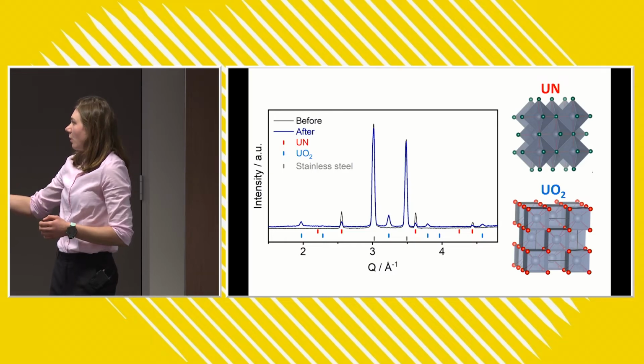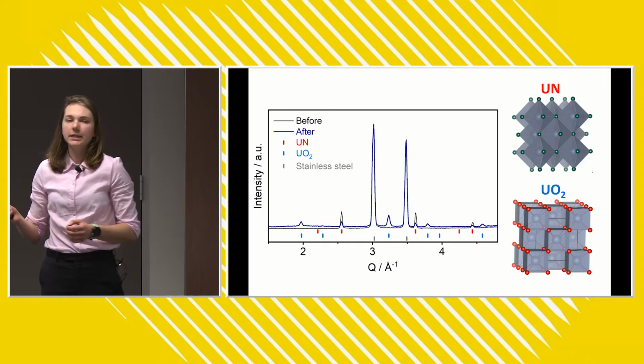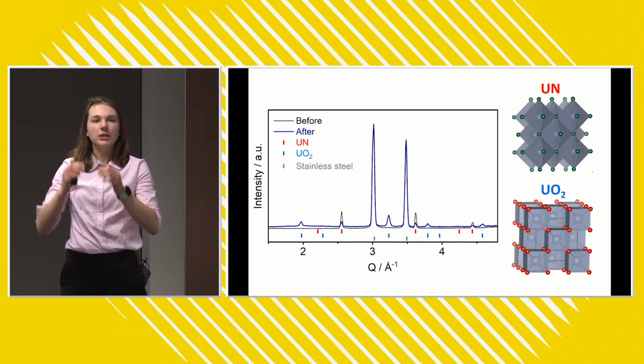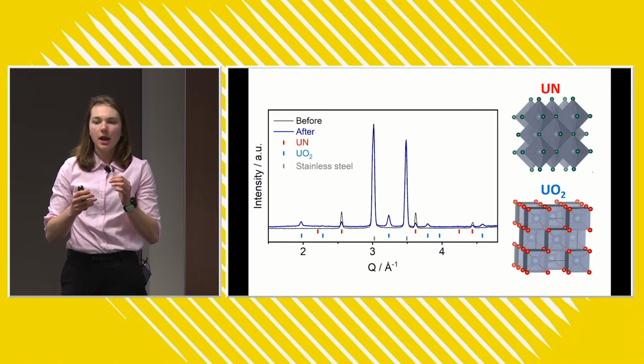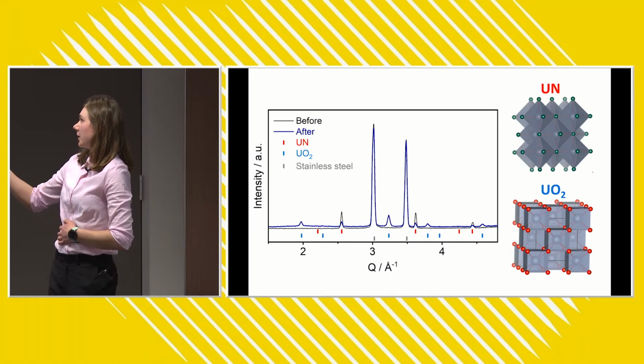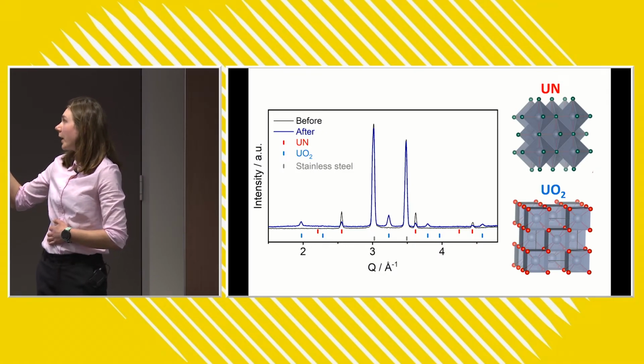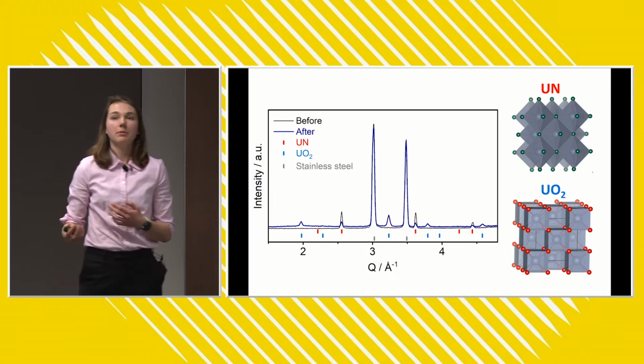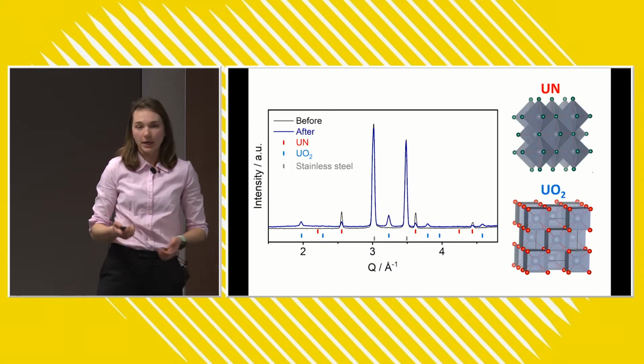And so we're collecting lots of this data, and we can see changes in those peak positions, and those changes tell us how quickly the uranium nitride, for example, is being converted to the uranium dioxide.